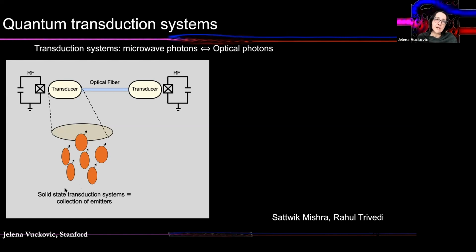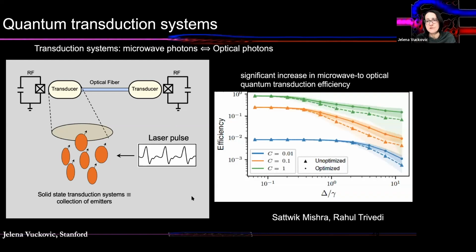So instead of tuning each one of them with a separate electrode or laser to collectively couple them, we thought about whether we could optimize our driving on the system in such a way that we improve transduction efficiency and recover superradiance in the system.